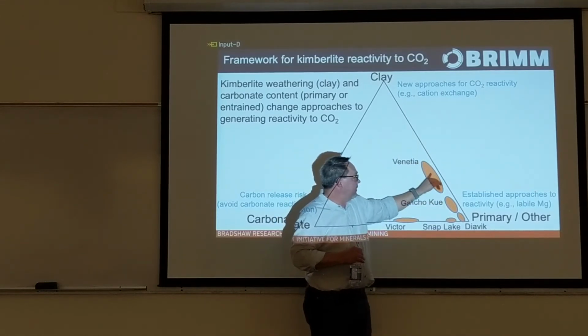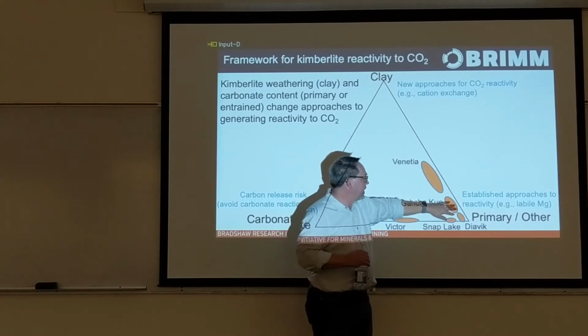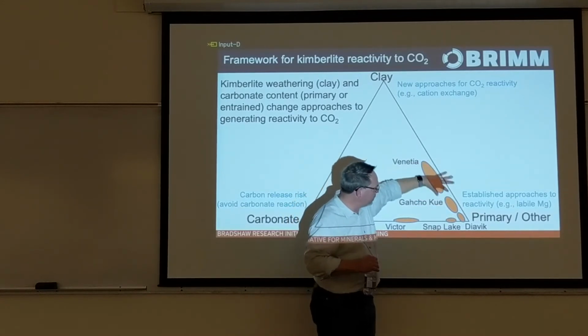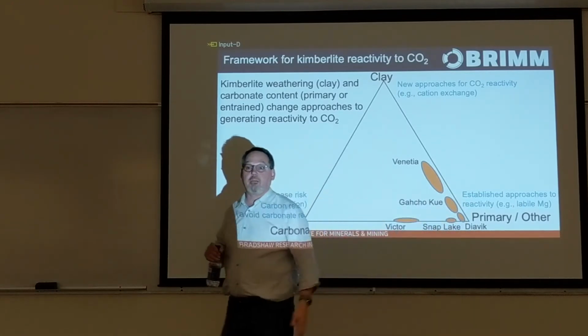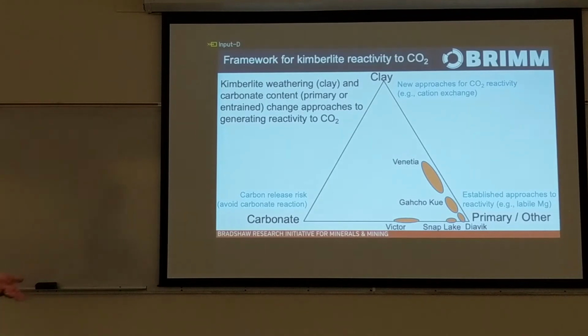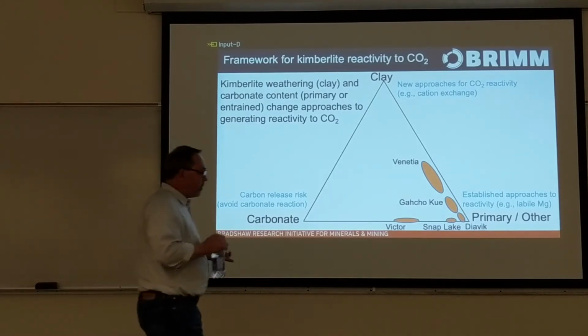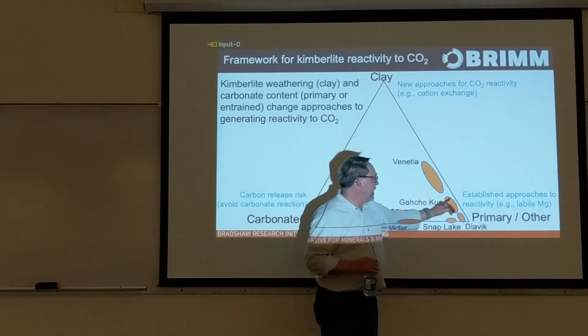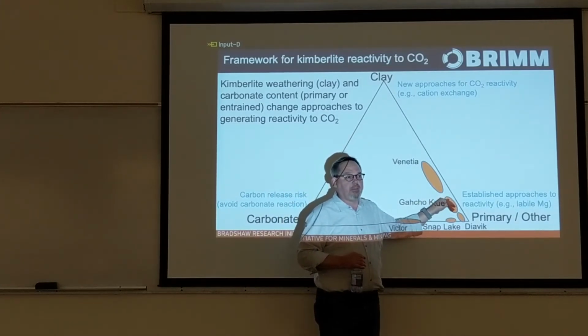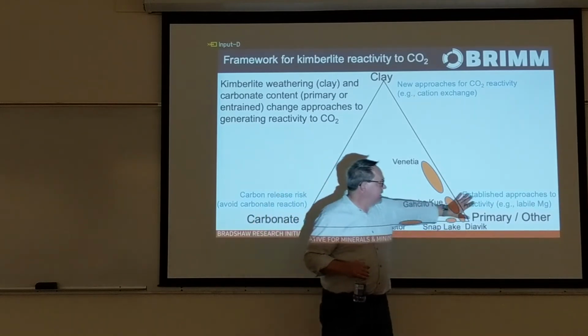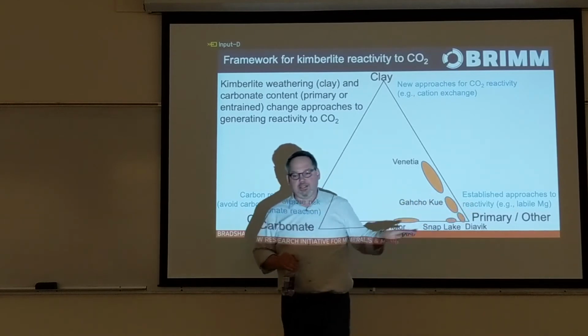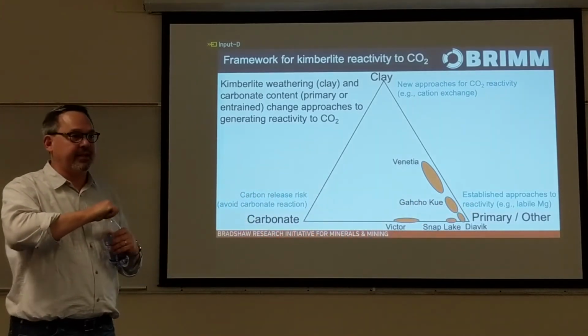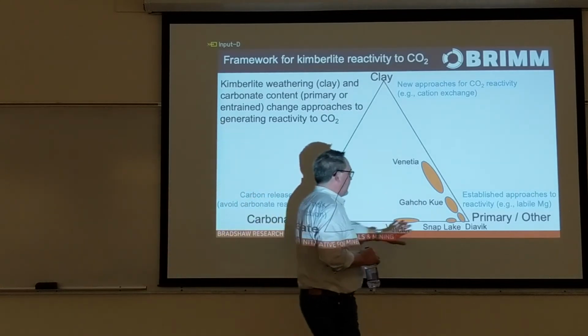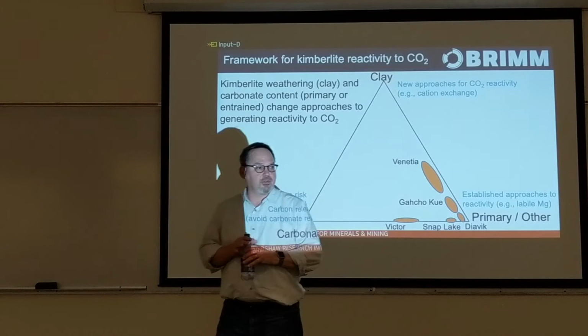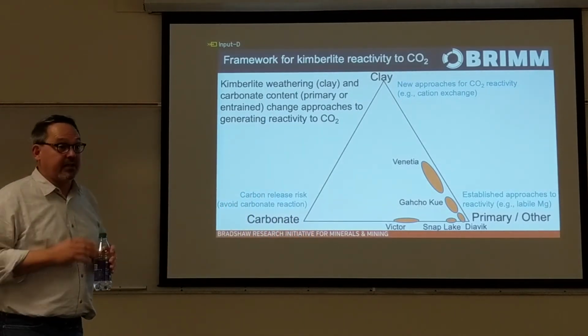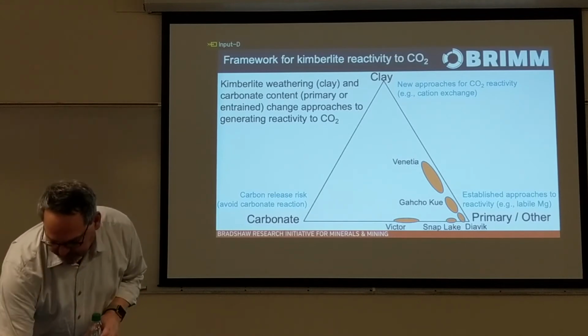Gahcho Kué and the future of Venetia, which is into much darker DDK, dark volcanoclastic kimberlite, moves us down towards this axis here. So what we are seeing is in the mine operations, as they go deeper into the darker and fresher material, we're seeing clearly they're moving in that direction at Orapa and Jwaneng and Venetia and at Gahcho Kué. These are actually from the very first year of operations, just that weathered cap, and already their material is moving down towards this axis. These are serpentine and brucite and hydrotalcite bearing tailings that are amenable to sort of the traditional approach that we've applied to date. But we walked into this thinking that kimberlite plotted here, and it was a big eye-opener in our first year to get an appreciation for the diversity within individual deposits as well as between them.